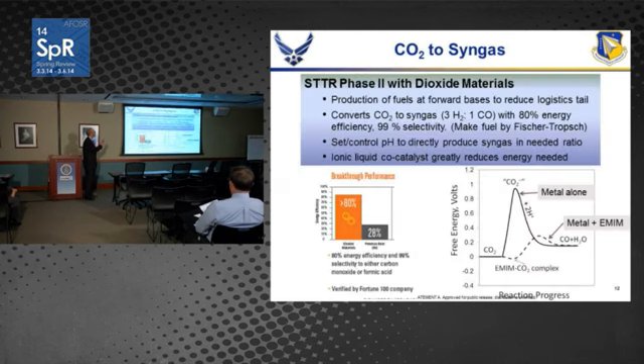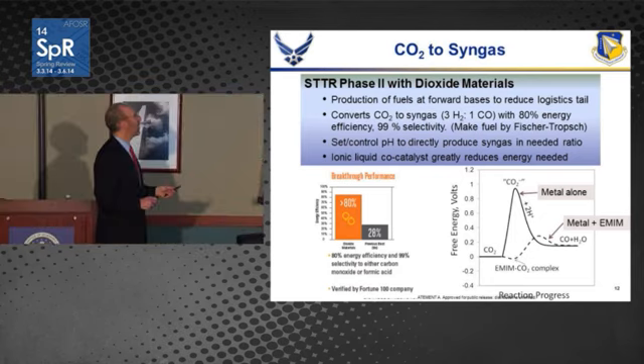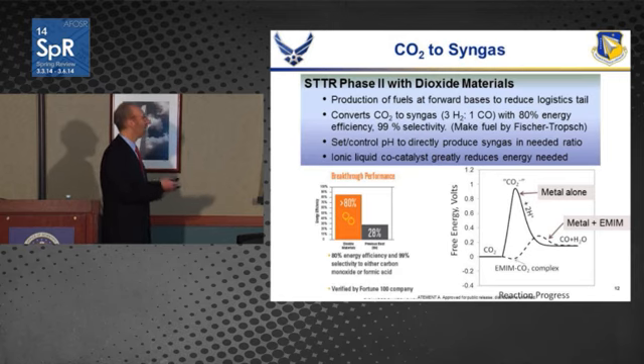So now I'll tell you a little bit more detail about the work that's going on in taking CO2 and converting that to syngas. This is done through an STTR program with a company called Dioxide Materials. Rich Masel is the lead of this company. And again, they've used an ionic liquid as a co-catalyst to work along with a platinum surface to greatly reduce the energy barrier for this process to take place.